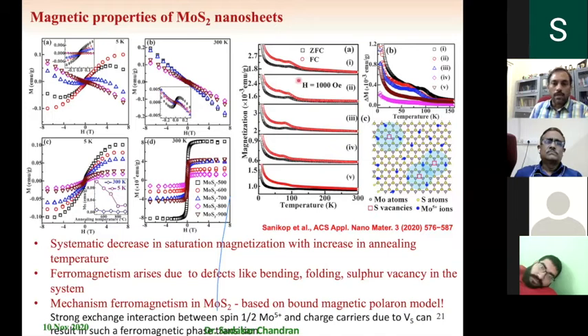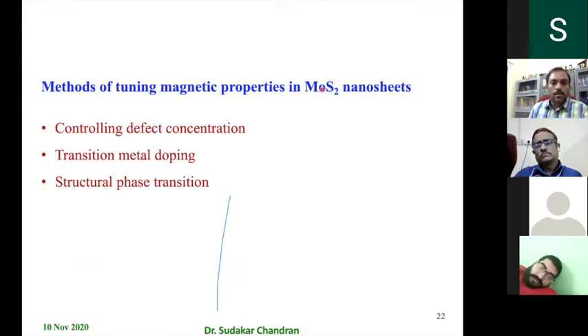In the temperature-dependent studies also, you can see the ferromagnetic-like transition seen around 120 Kelvin. And we believe the ferromagnetic nature is because of the dilute magnetic-like situation in these nanosheets. In fact, this is only pure MoS2, no magnetic dopants were there. Therefore, we wanted to see can we tune the magnetic properties by controlling other ways, the defects, like transition metal